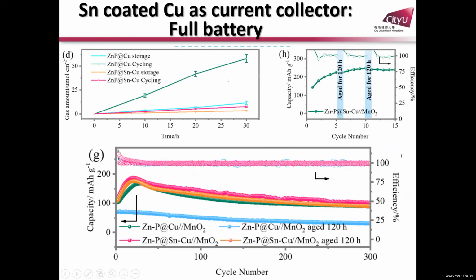So we're trying to solve this problem by coating copper with tin, so that the copper itself acts as the current collector. With the tin coating, you will see the problem is partially solved. I'm not saying it's totally solved. You still have hydrogen evolution, but it is much better with the coating.